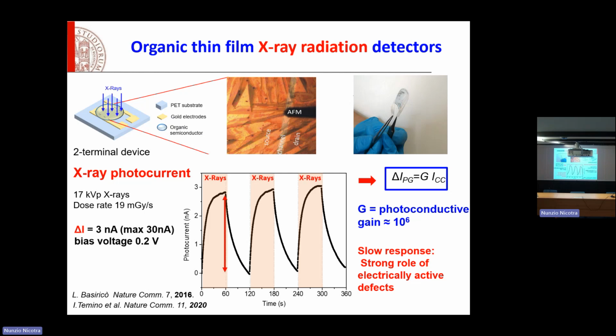So this is a very good signal to be read by an electronic readout, so it's not a difficult signal to read. And what is very interesting is two things. First of all, the slow response. The slow response is basically telling us that there is a strong interaction between defects in the material. The slow response is related to the trapping and detrapping of defective states that have a long lifetime and that are known to exist in organic semiconductors.